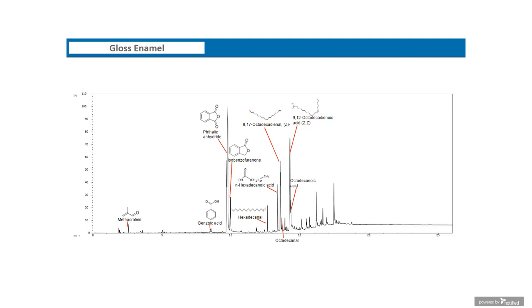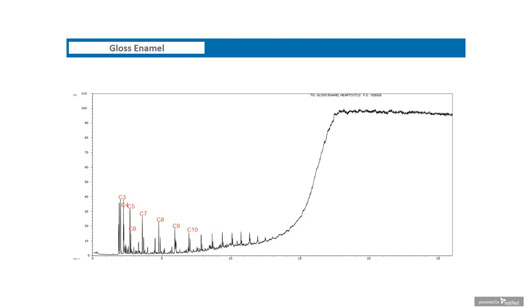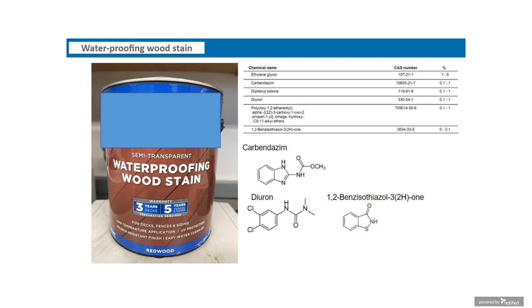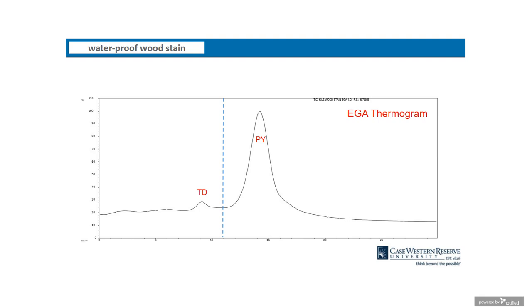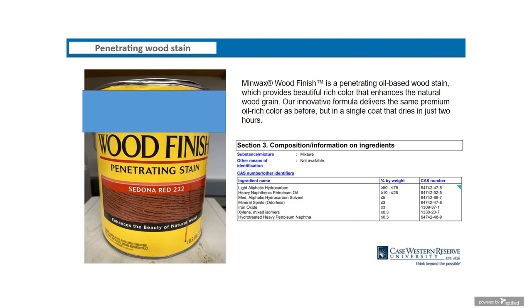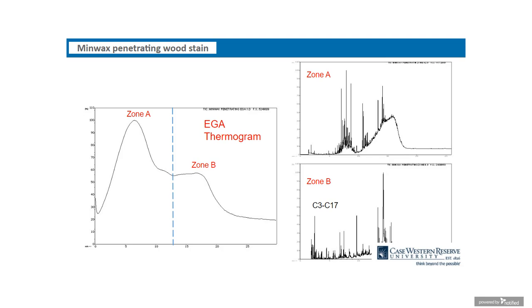This enamel composition could be various types of resins or alkyd resins that we typically use in the manufacture or formulation of enamel paint. And the presence of the long alkyl chain compositions was confirmed by this mass spec as well. So again, I'd like to leave more time for questions, and I'd like to finish here by saying that in GC mass spec pyrolysis, we have the ability to rapidly reverse engineer, quote unquote, a competitor sample, a supplier, a commercial sample that we can use for R&D research or publications use.